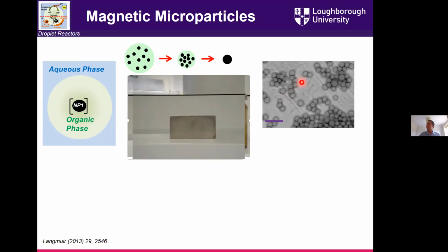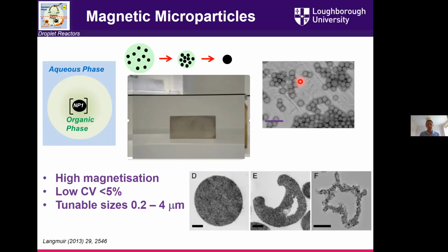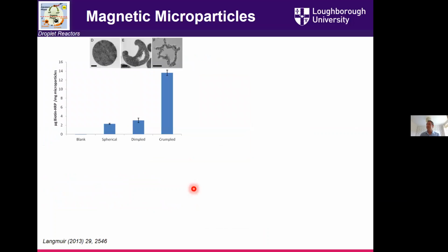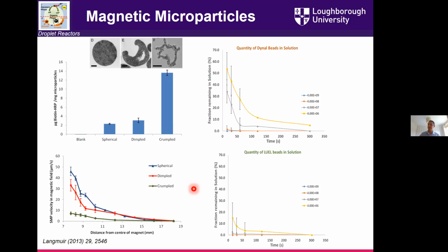And by going through this process, you can make them quite monodisperse, you can control the size of the emulsion droplets. In theory, you can control the evaporation rates and the loading of the material, and you can really play around with the size and some of the physical features in terms of their shapes, and then apply that to sensing methodologies. And what was interesting in the work that we were doing in Dublin is that if you change the shape, their drag through solution as you apply a magnetic field changes their extraction speeds, it changes the surface area. So if you're looking to extract analytes from solution, having some control over the surface area is important, because then you can extract different amounts.